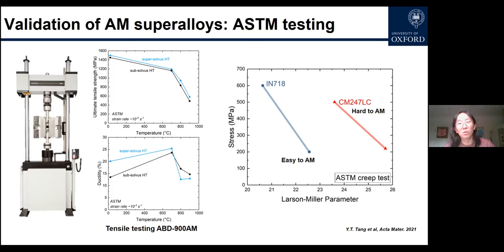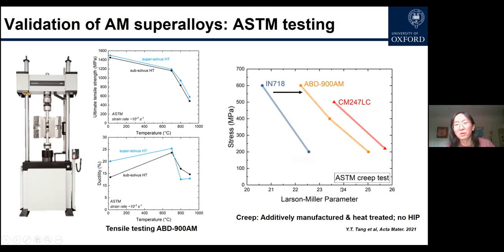So what we want in the ideal world is to have something as printable as 718, with the same properties as 247. And in this diagram, which is called the LMP or Larson Miller parameter plot, the farther to the right, the better the properties are. And whatever these numbers here are telling you is basically about one order of magnitude. In that regard, our alloys are not doing too badly, and we are basically approaching this line to its capacity.